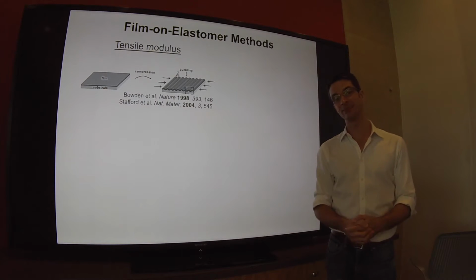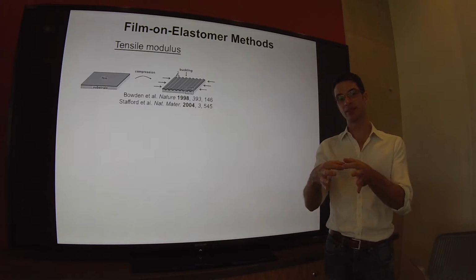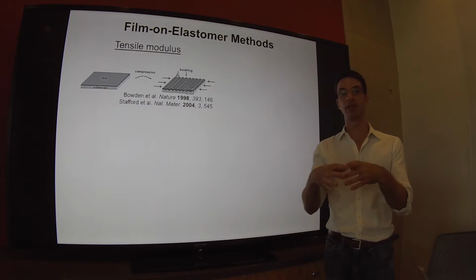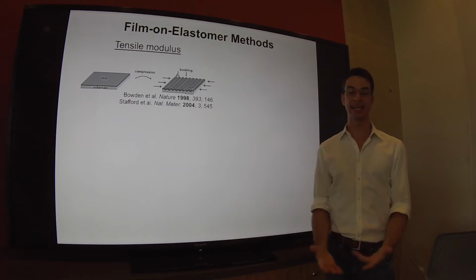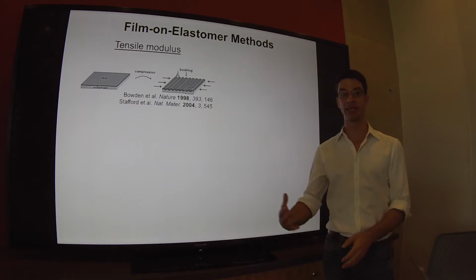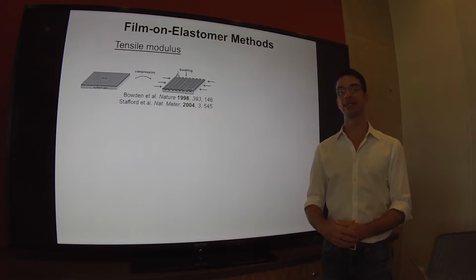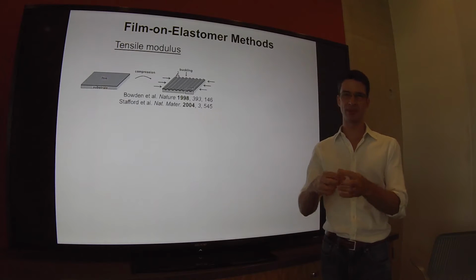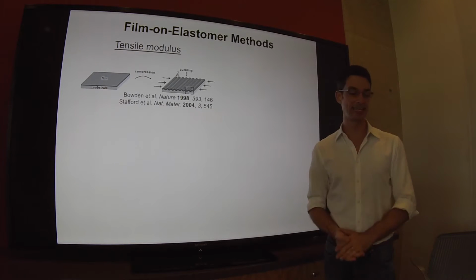And the reason is because, number one, it's hard to manipulate a freestanding film, and number two, if you're working with synthetic chemists in your research group, you might only get a few milligrams of material at a time, so it's very difficult to form a bulk piece to get a tensile test.